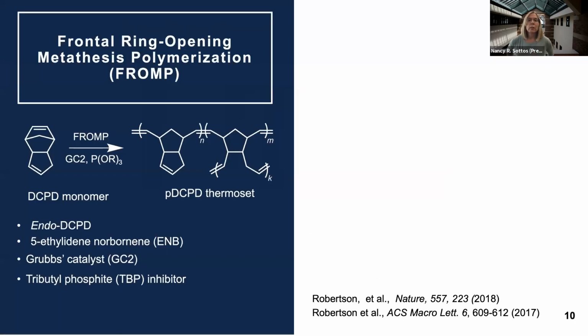But let me start out with the chemistry that our group has been focusing on, one particular monomer. And that is the monomer dicyclopentadiene, or DCPD for short, which you see over here. And we initiate a frontal ring opening metathesis polymerization using Grubbs catalyst, in particular GC2.